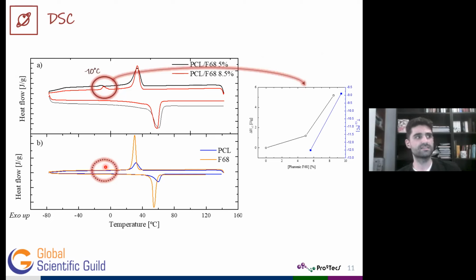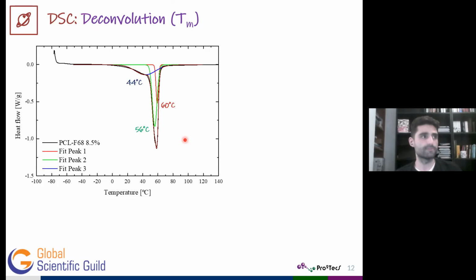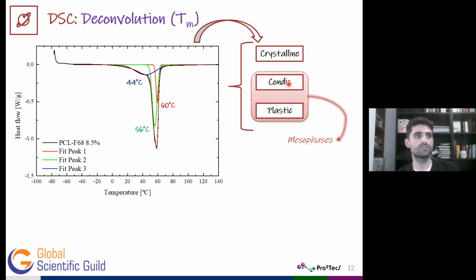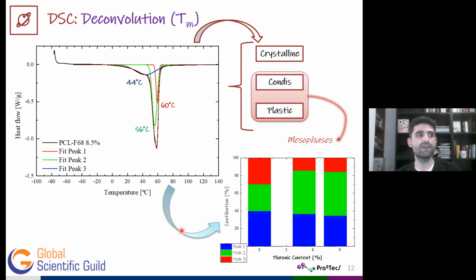Well, in order to delve into the impact of adding Pluronic into neat PCL, we applied a deconvolution of the melting peak, and we suitably deconvoluted that peak into 3 individual Gaussian peaks, confirming what we found in the literature, that not only the crystalline phase, but also some partially ordered mesophases can be found, containing condis crystals or plastic crystal morphologies. Indeed, we couldn't identify to which of these peaks those crystal morphologies corresponded, but we observed that although all these 3 peaks appear in all cases, not only in the polymer blends but also in pure PCL, the addition of Pluronic modified the individual contribution.